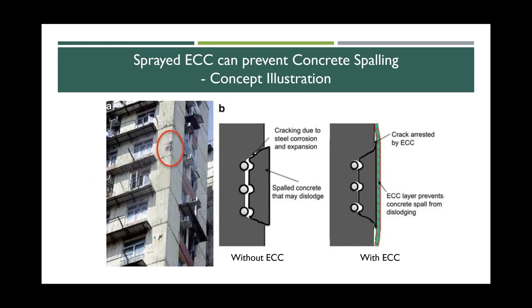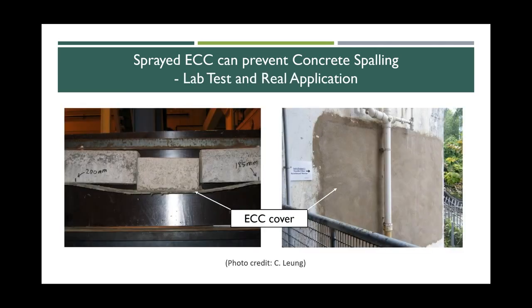So in order to prevent that, in Hong Kong, we proposed some ideas to spray a layer of ECC on top of that, so it can prevent concrete spall. And that is a conceptual illustration. Let's take a look at the lab test. You see that even after this concrete drops, it's basically 3 blocks, it drops, the ECC can still hold it, and then we apply one on the wall. But once it bulges, if you see the ECC cover bulge, you know there must be some problems over there, and you have to go repair. So this is one of the things that can improve safety, preventing concrete from falling from high-rise buildings.